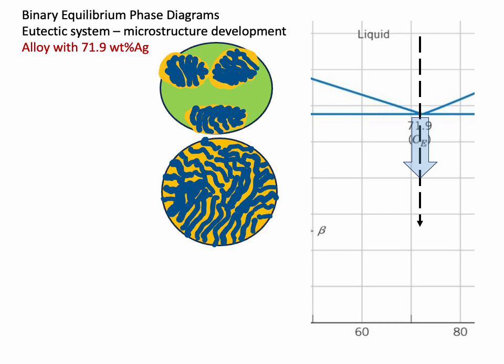But if I have my fluid liquid state and I'm cooling and I cross the eutectic temperature, then liquid is no longer stable, and the system is trying to make something happen. And so what will happen is I'll start to form a layer of one of the two phases, and it'll grow in away from where it nucleates.